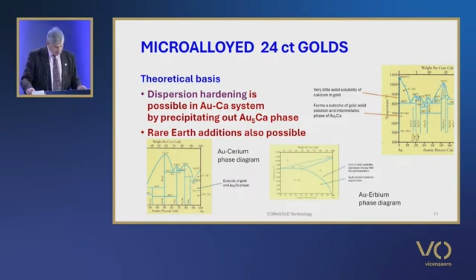Another alloying approach would be to add rare earth metals such as cerium, lanthanum and dysprosium, or gadolinium, as these also tend to have limited solid solubility in gold and to form eutectics and intermetallic compounds with gold. Some of the relevant features of their phase diagrams with gold will be shown in the next table. Some rare earths have been omitted from this table just for brevity.